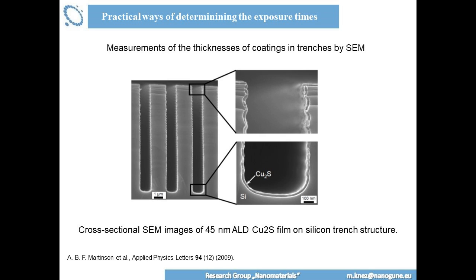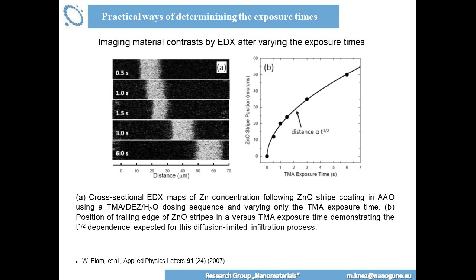There is copper sulfide deposited on top and bottom, and they were just comparing the thicknesses here. And the thicknesses differ only by a small error. It means the coating, the process setup, was really good. Of course, the pores here are rather big. In ALD, you sometimes really go to much smaller structures, so it becomes more difficult to really look into that. But okay, SEM is a really good tool to take a look into the thicknesses.